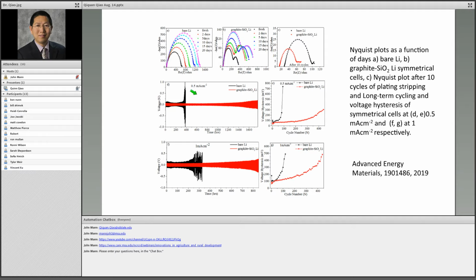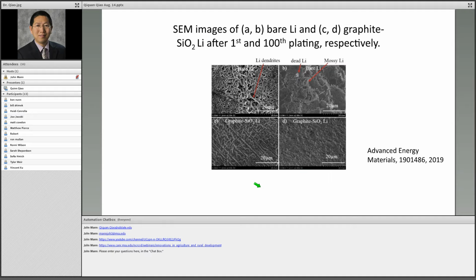The same thing, this one is at a lower charging rate. At a higher charging rate, you can see it can be improved from about 300 to 900, a significant improvement in lithium metal battery performance. And here, without this graphite or silicon dioxide, you see a lot of dendrite growth, or these needle things. See here, right? Once you have this graphite silicon dioxide protection, you see the surface become very smooth, and you don't see any needles here.